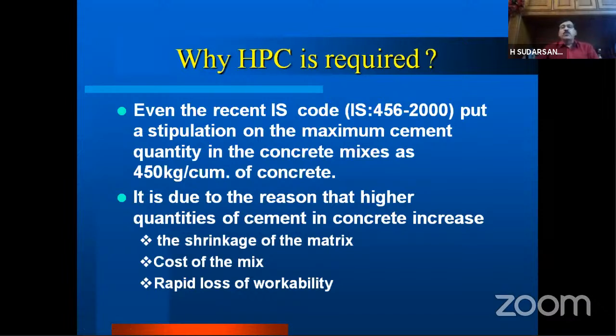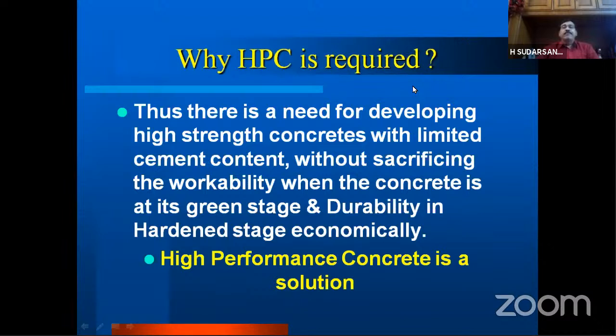Even if you look at the IS code IS 456-2000, they have put a stipulation on the maximum cement quantity to be used in the concrete as 450 kgs per cubic meter. So there is a stipulation, that is a maximum limit, 450 kgs. You cannot cross 450 kgs to produce any concrete of whatever strength you want. Because this restriction is brought in, this higher cement content in the concrete can cause the shrinkage of the matrix, increase in the cost of the mix, and also a rapid loss of workability. So due to these reasons, the code has put a restriction on maximum cement content.